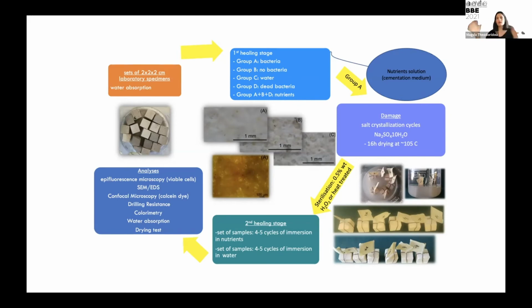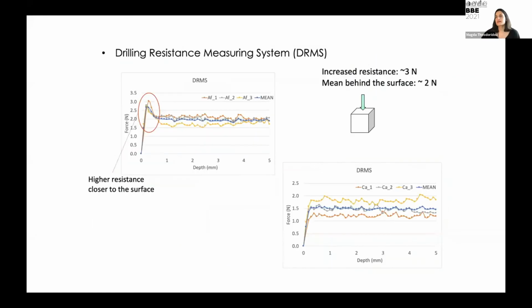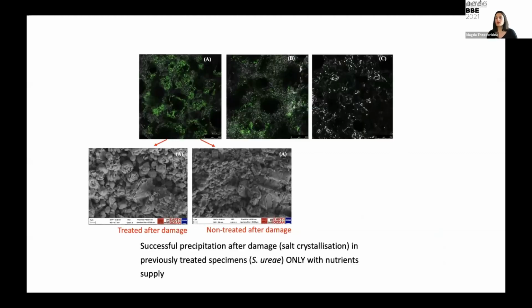And then the whole set of analysis and tests was performed again after the second healing stage. And here you can see that DRMS confirmed the ability of this bacteria to cause mineral formation at the area closer to the treated surface compared to the control samples, which you can see in the right-hand graph. We can also see that confocal microscopy proved strong evidence of newly formed calcium carbonate in Group A.